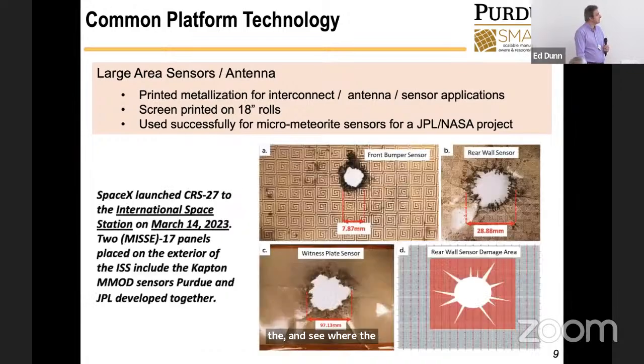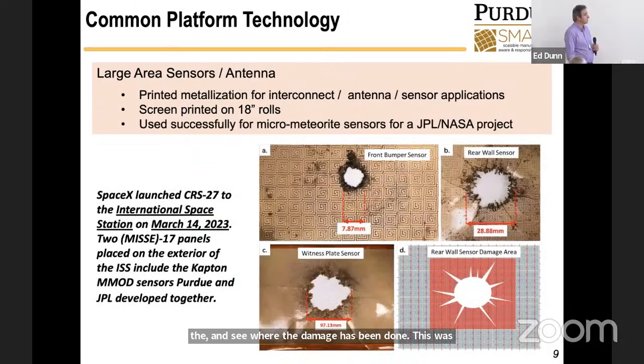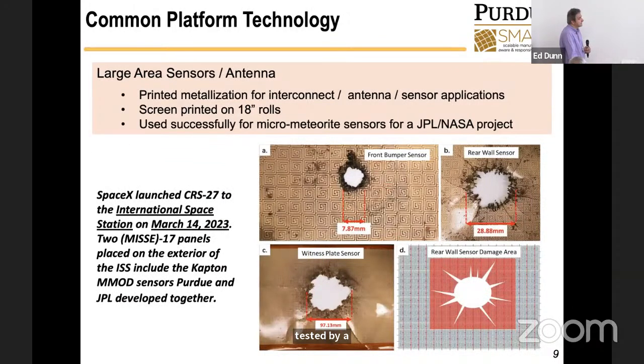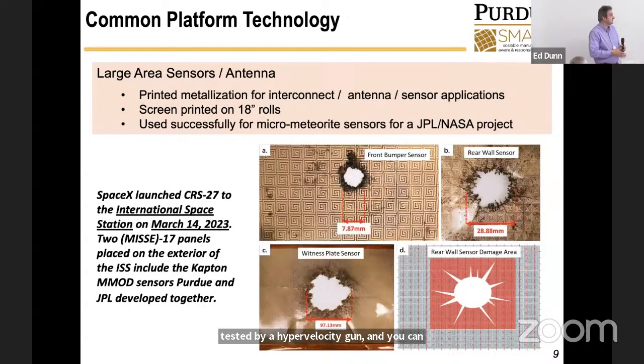This was tested by a hypervelocity gun. You can see that there are 3 layers. The first layer has damage of about 7 millimeters from, I think, a 3 kilometer per second bullet that was fired into the sensor. And as the bullet goes in, it makes bigger and bigger holes. It opens up like a cone.